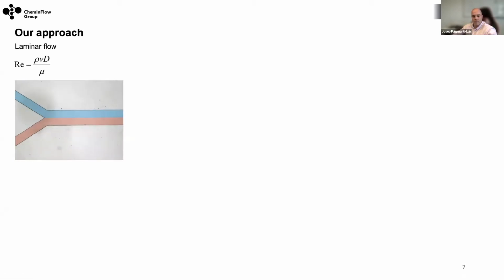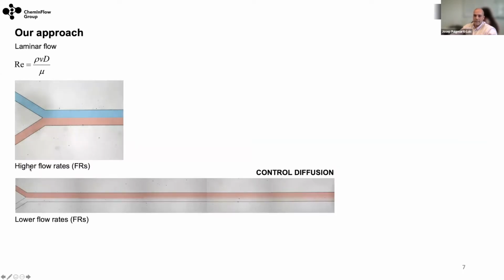But more interestingly, this happened because we had high flow rates here. When we decrease the flow rates, we can decide how much we want this dye to diffuse towards this aqueous stream here. So what you see now is that all along the main microfluidic channel, which is around 250 micrometers, we can control the flow rates so that the dye will diffuse completely towards the other side of the microfluidic device.